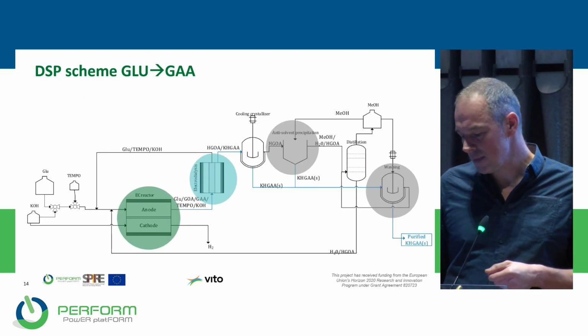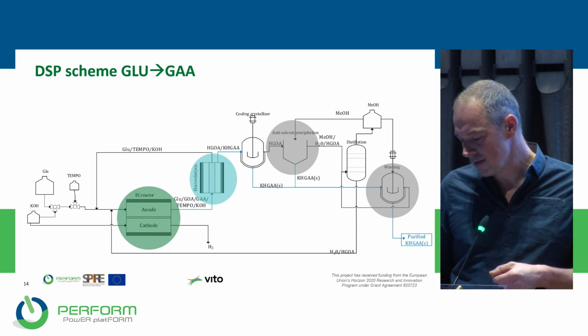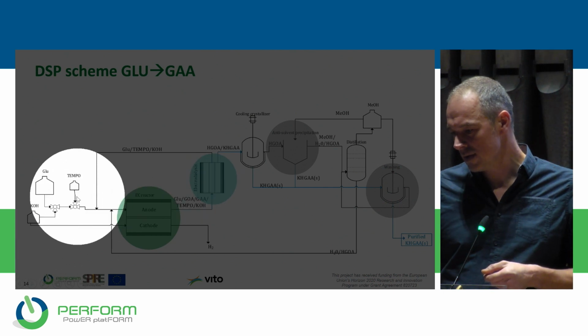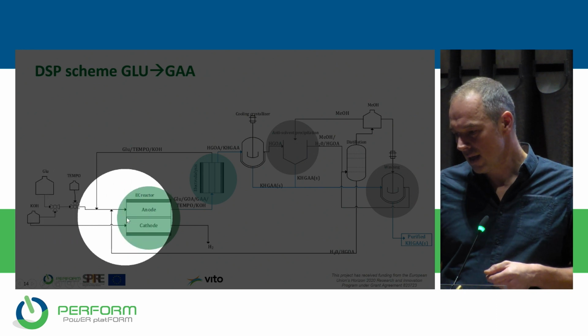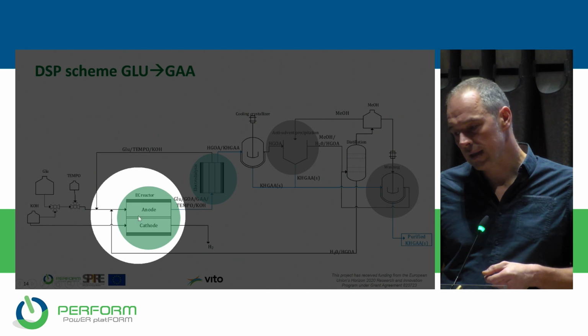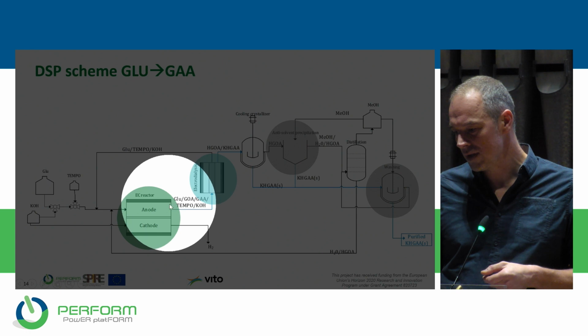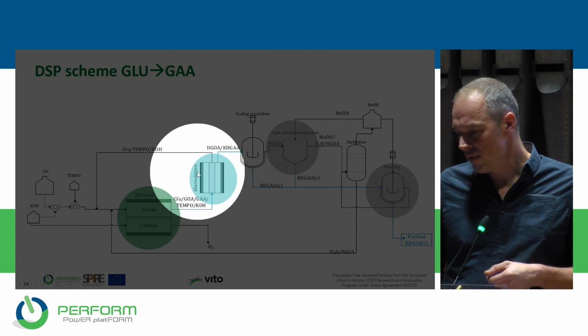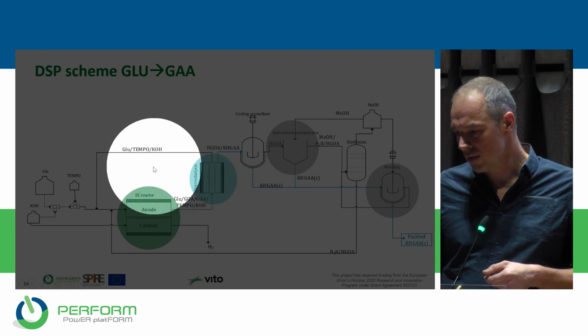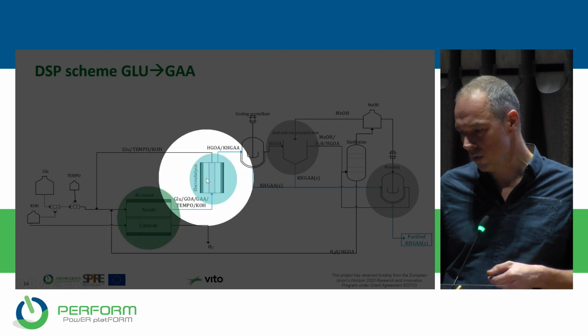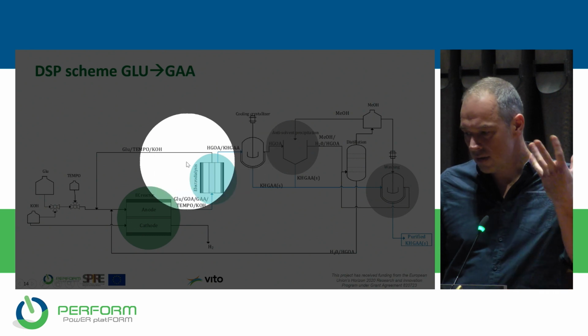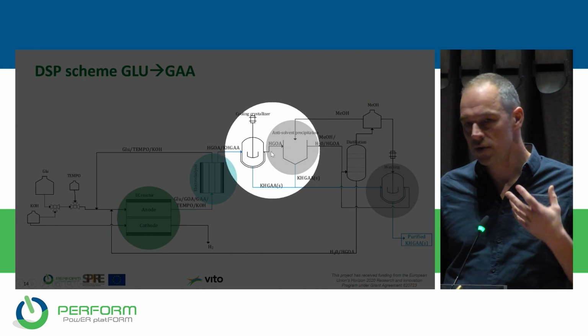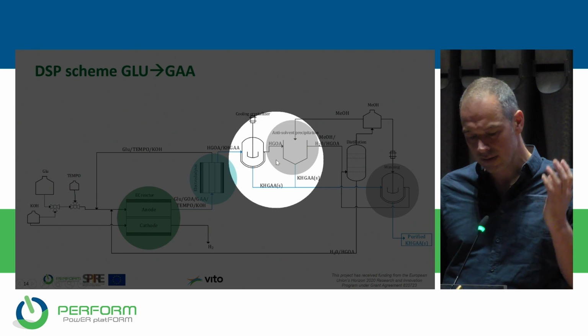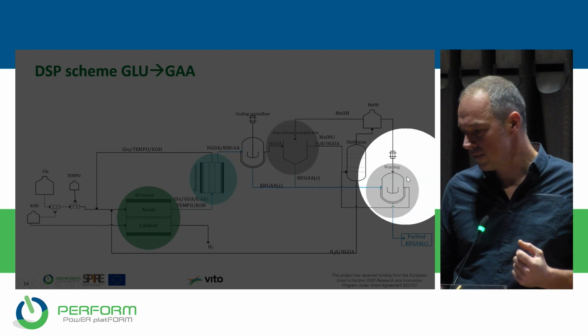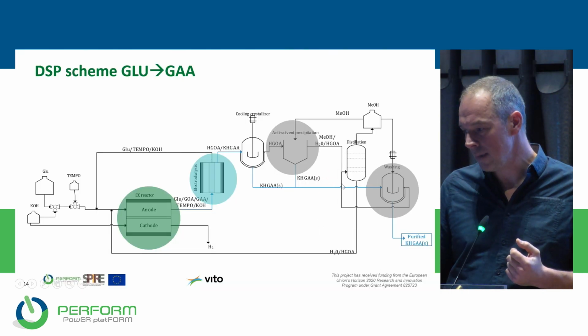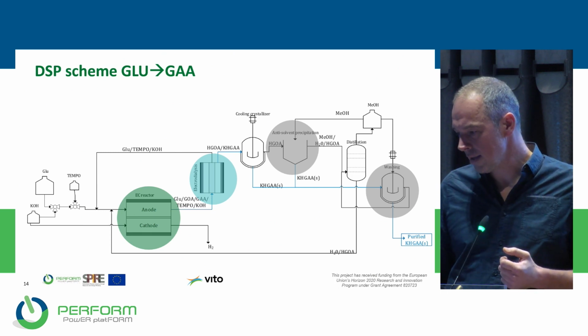So this is what the total DSP scheme will look like, starting from the feed, which is glucose, TEMPO, and base, in this case potassium hydroxide, where we go to the electrocatalytic reactor, where glucose is oxidized to gluconic, which is GOA, and glucaric, GAA. Both are then separated in an electrodialysis unit where the glucose, TEMPO, and the base are recycled back to the reactor. So no loss there. The gluconate and glucarate are still combined in the solution, and they go to a crystallizer using the anti-solvent precipitation, where we are able to separate the glucarate again from the gluconate. All this methanol, which is used in this cycle, can be recovered and recycled.